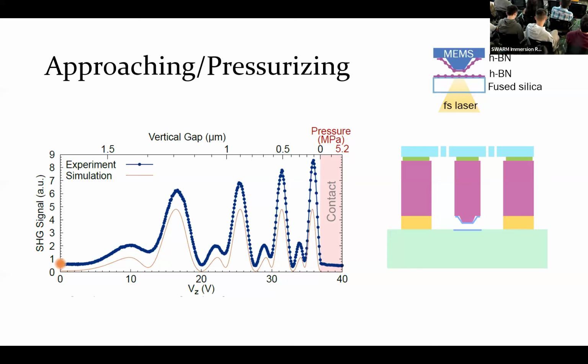So it doubles the frequency of the light because the hexagonal boron nitride breaks some internal symmetry, and we can use that process to monitor the operation of these MEMS devices. So this shows the experimental scheme here. Basically, we have 2 layers of hexagonal boron nitride, just as I showed you in the video. We have one tented on the pyramid, and the other one just flat.